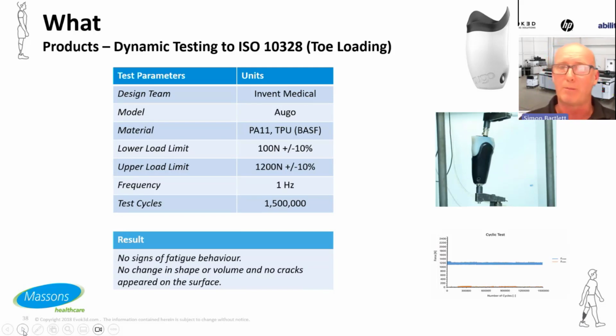But testing to those same parameters, as we assume for all the other items which bolt onto it, Invent Medical printed in a number of different materials, PA11 and TPU, and it surpassed 1.5 million cycles. So it's gone beyond testing requirements for all of the componentry that adds onto it. There were no signs of fatigue behaviour, no cracks, and no change in shape. Any deformation was elastic and not plastic. So that's a positive in terms of dynamic testing.